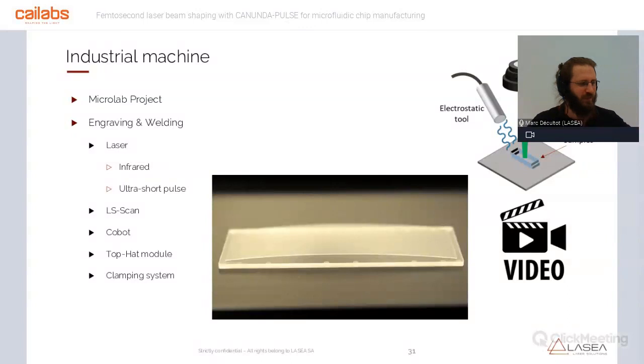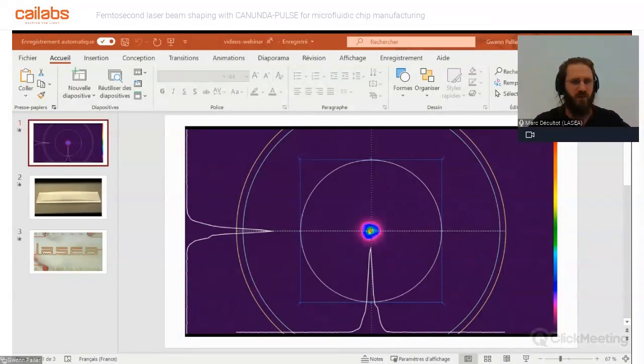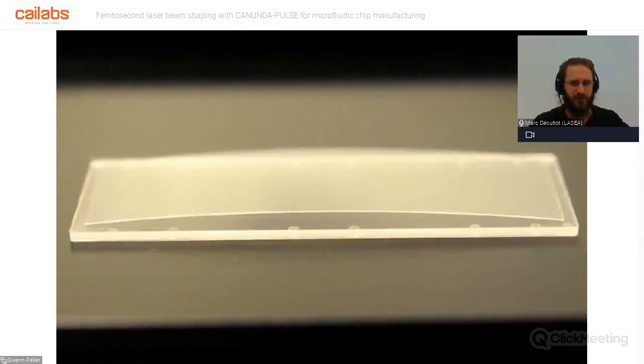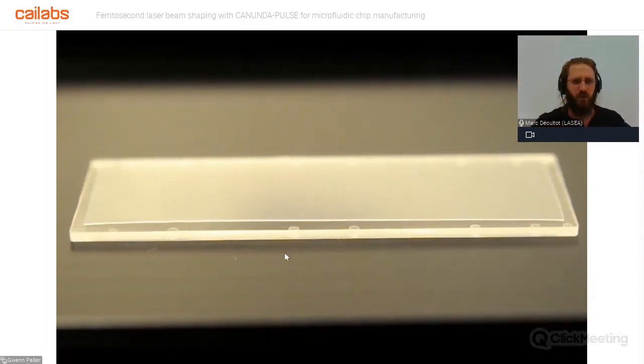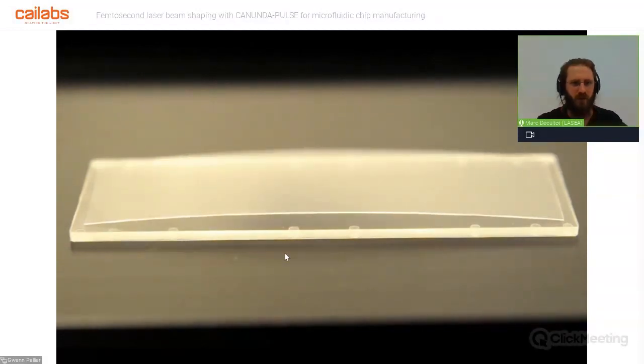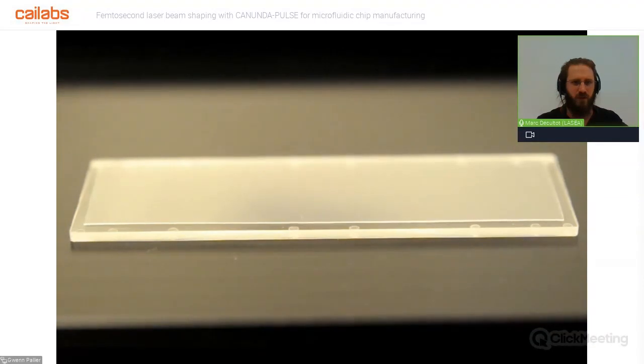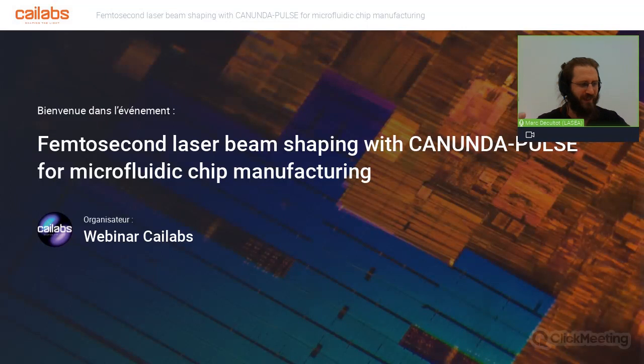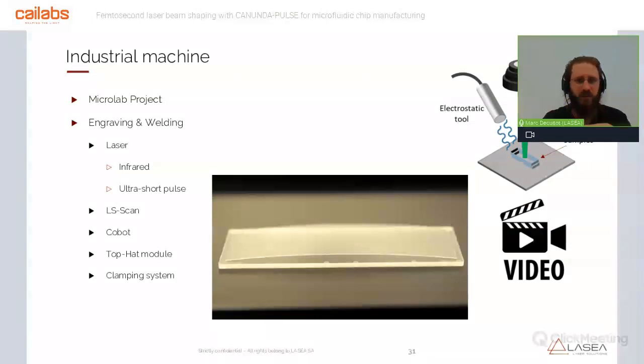And the clamping system, as you will see in the video, is able to push the film onto the chip without any contact. So here, without any contact, we put some electrostatic charge, and the film will push itself onto the chip. The clamping system is really important for welding, because the quality of your welding will depend directly on the contact between the film and the chip. Thanks to the electrostatic clamping system, we achieve a strong and homogeneous clamping force.